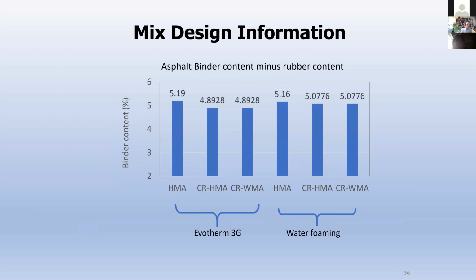So here is the material we are doing for these two things. This is hot mix asphalt. This is warm mix, and of course with rubber mix as well. This is rubber hot mix. This one is rubber warm mix. Warm mix normally is about 30 degrees lower in temperature. So during production, you are going to use less heat, less energy. That really is a good thing, because you are going to have less emission to the air.